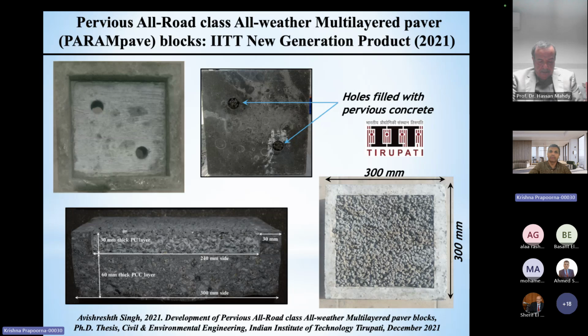So if you want to have M50, you manufacture that base with concrete and then impregnate this small portion with pervious concrete. You see here, this is a 90 millimeter height of the concrete block that you create using a mold, a square mold that you see here. Impregnate this groove with pervious concrete. And these holes also are filled with pervious concrete. That is something that you want to be aware of.